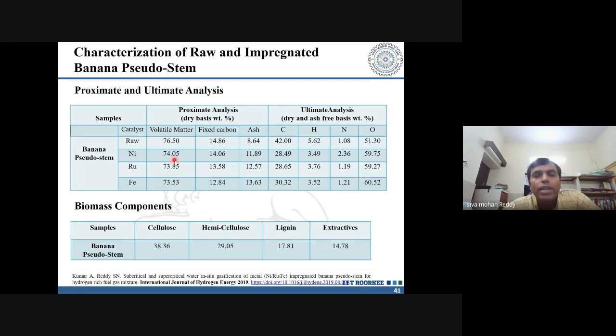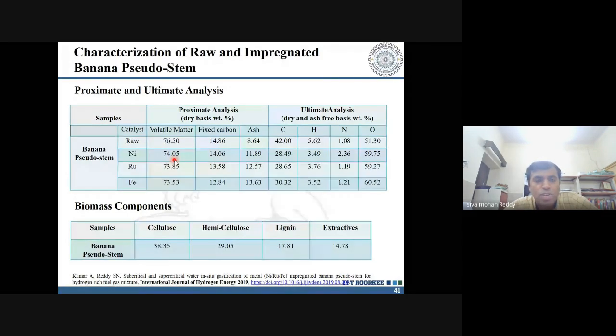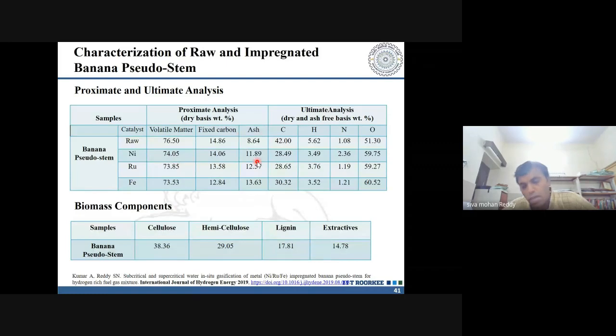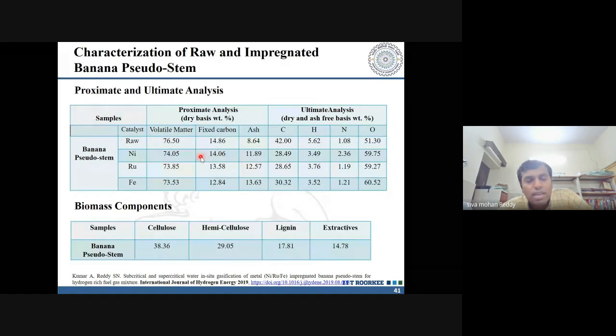So before we go into more detail about the thermal degradation, one has to perform proximate and ultimate analysis to identify the volatile matter content and fixed carbon content. So you see that the volatile matter content is around 76.5% for banana pseudostem. Fixed carbon is around 14.86, and its ash content is 8.64 for raw biomass. Now, as soon as you impregnate with metals, since metals fall under the category of ash content, your ash content is significantly enhanced, which tells us that some loading of metals occurred during the impregnation process.